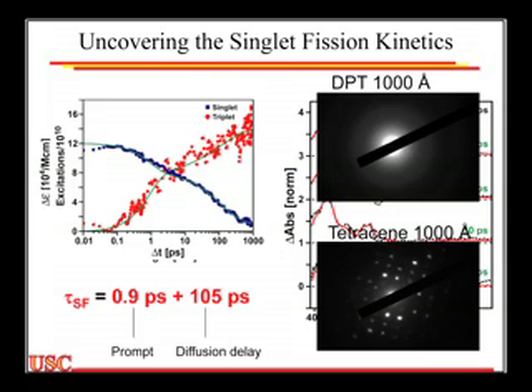The reason we have this bi-exponential character is, remember, this is an amorphous film. It doesn't show up so well here, but the bottom one is tetracene, the top one is DPT. This is in the TEM. This is the best I can do to prove to you that it's amorphous, but we see no order in either the X-ray diffraction patterns or the electron diffraction patterns. But the key is it's an amorphous material, and we don't believe that you can do singlet fission everywhere in the solid, but there are certain points in the solid, defect sites or ordered sites, where you can do it.